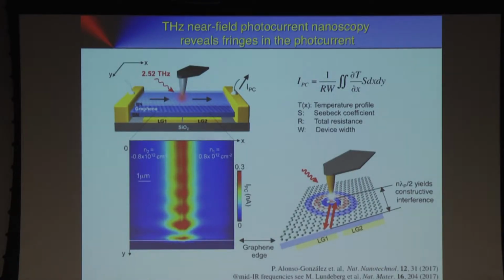I also mentioned terahertz, and terahertz is also triggering a lot of interest. But in terahertz, we have a couple of problems. Terahertz wavelengths are really long. We're talking about 100, 200, 500 micrometer wavelengths. And so if we scatter light at this 10 micrometer long tip, then the scattering efficiency is very weak.